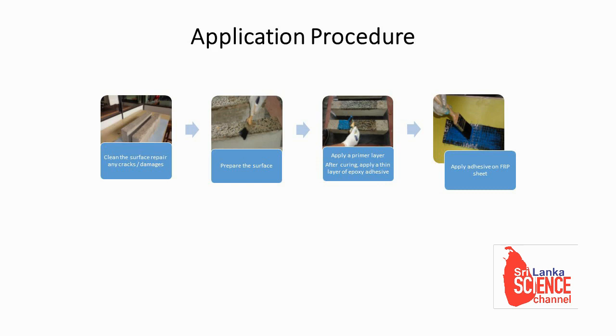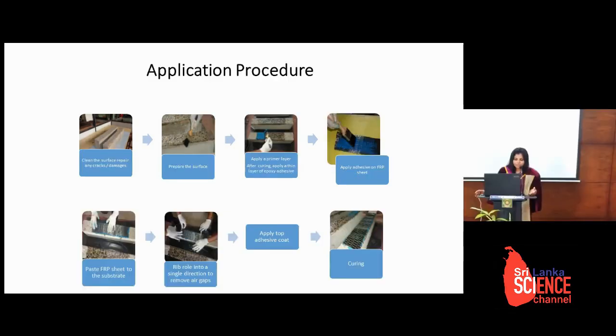There are two popular methods: the wet layup method and the dry layup method. If you follow the wet layup method, which is most popular in our country, we have to apply adhesive on the substrate and also on the CFRP material, then press it onto the surface and roll it in one direction to expel air bubbles entrapped in the bond line. And we can apply a top coat after completing the application and cure for at least 7 days according to the manufacturer's guidelines.